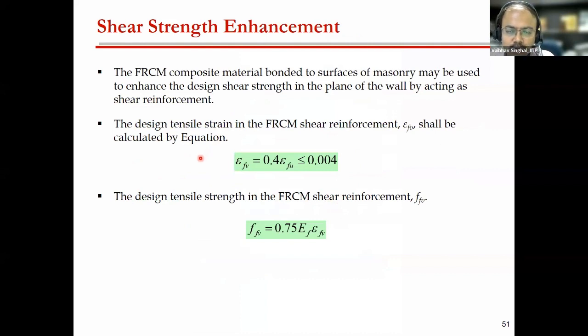So instead of going into a lot of tests, they directly suggest that effective strain can be taken, as an upper limit, as 0.004. But some secondary thought is required for this, because from a lot of tests and from the literature, various data which are available, it is seen that this value seems to be quite low, and there will be a good amount of underestimation in the strength if we consider this value of effective strain in the design.